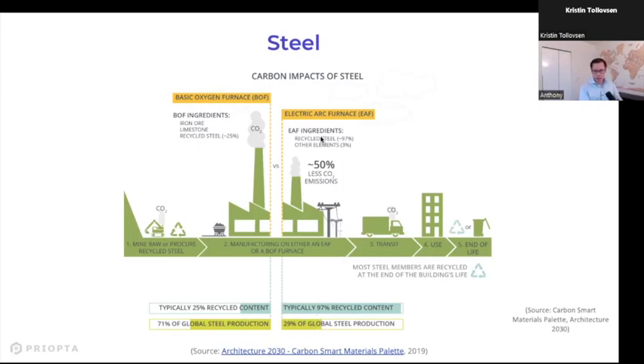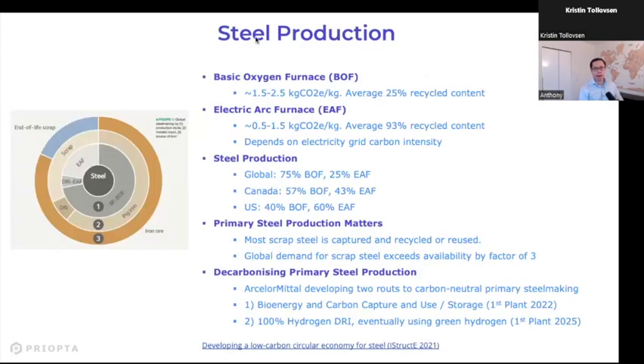Now, on a project level, you could definitely specify electric arc furnace steel or higher recycled steel content on your projects, which would obviously reduce the emissions. But something to keep in mind is that there's not enough recycled steel in the world to meet all of global demand. So it's still really important for us, as a society, to think through how we decarbonize primary steel production as well. I've just given you some high level stats, from the numbers that I've seen. Basic oxygen furnace is typically 1.5 to 2.5, maybe even 3 kilograms of CO2 per kilogram of steel, whereas electric arc furnace can be 0.5 to 1.5 kilograms of CO2 per kilogram of steel.